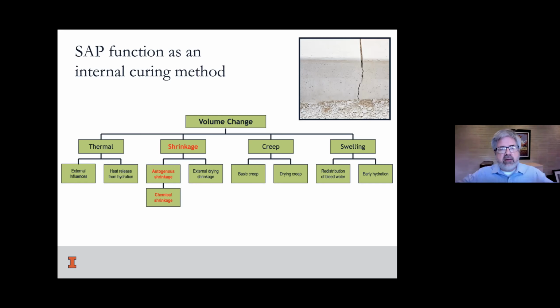And then as the concrete mixes and goes through a setting process, these little beads or little locations of swollen SAP will stay in the microstructure, reside in the microstructure until they lose the competition. That is, the hydration of the cement is going to kick in, is going to start fighting for water, and it will pull it away from the SAP when the time comes. And hopefully we've got the structure of the concrete all set and established, and that water is seen as like an extra reservoir to the paste as it goes through hydration.